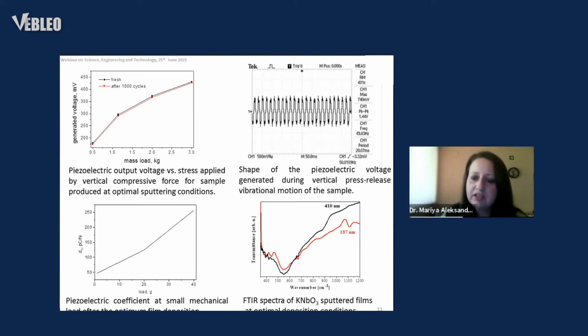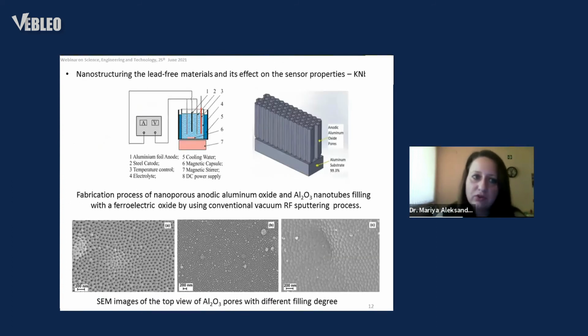And by Fourier transform infrared spectroscopy, we are able to detect the reason for this strong piezoelectric response. It is due to the presence of several non-centrosymmetric lattice formations, unit cells. They are more asymmetric than the pure cubic, and they are tetragonal, orthorhombic, and rhombohedral lattices. So I will not go into the details.